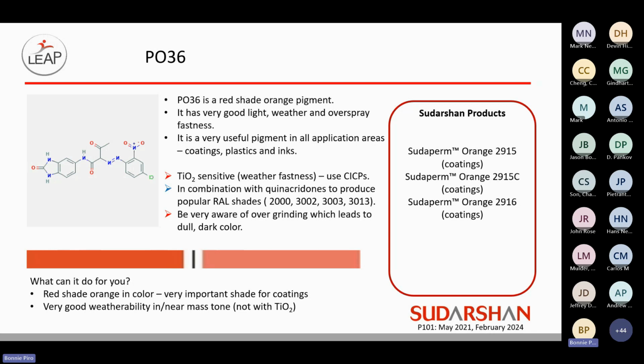But I caution users to make sure that you are not overgrinding it because it's a very soft pigment, so it can easily be overground to a dark and dull color. As a formulator, it offers that very red shade orange in color, and it gives that shade that's required. And you can get around the TiO2 issue using potentially CICPs to improve that weatherability.